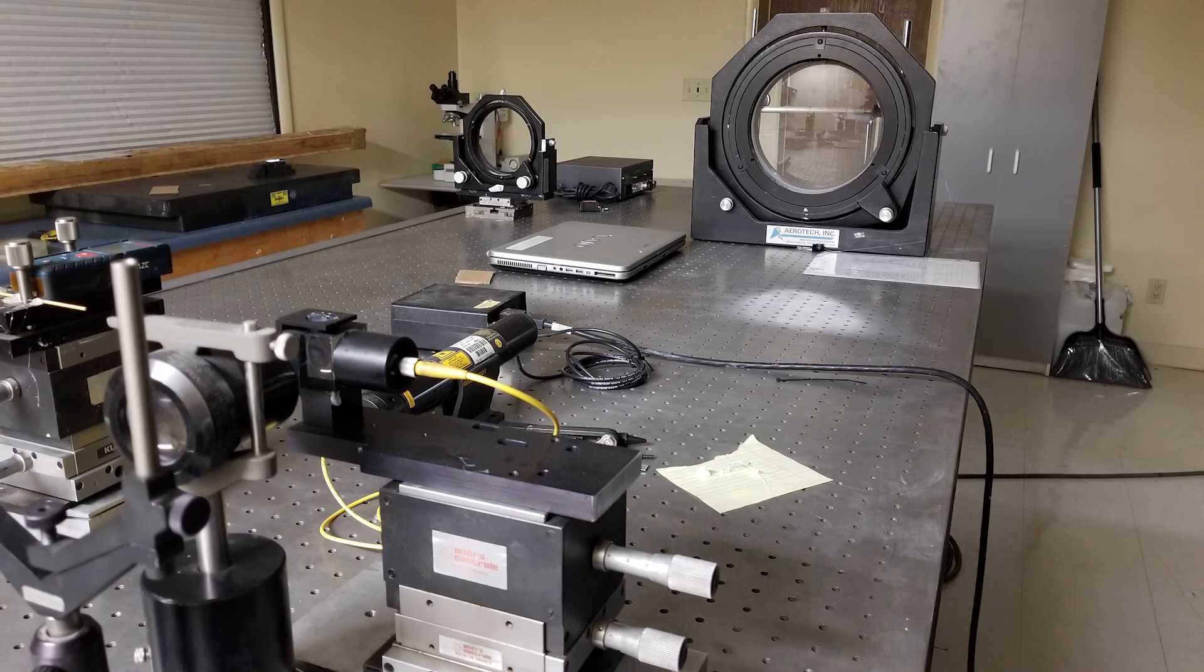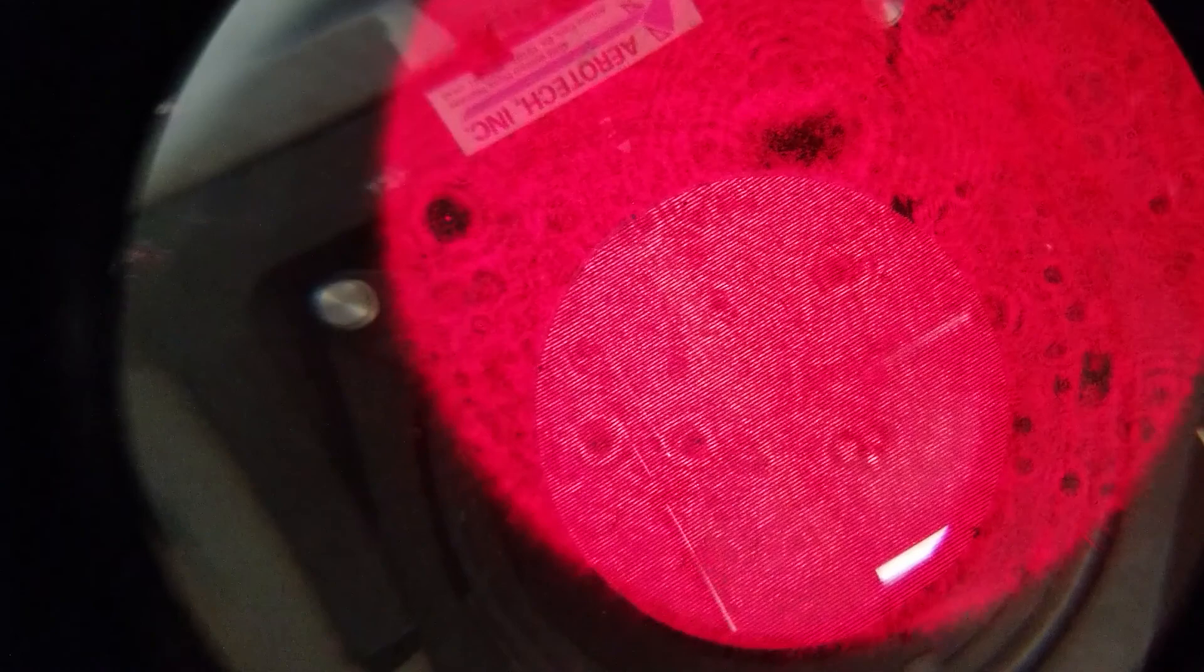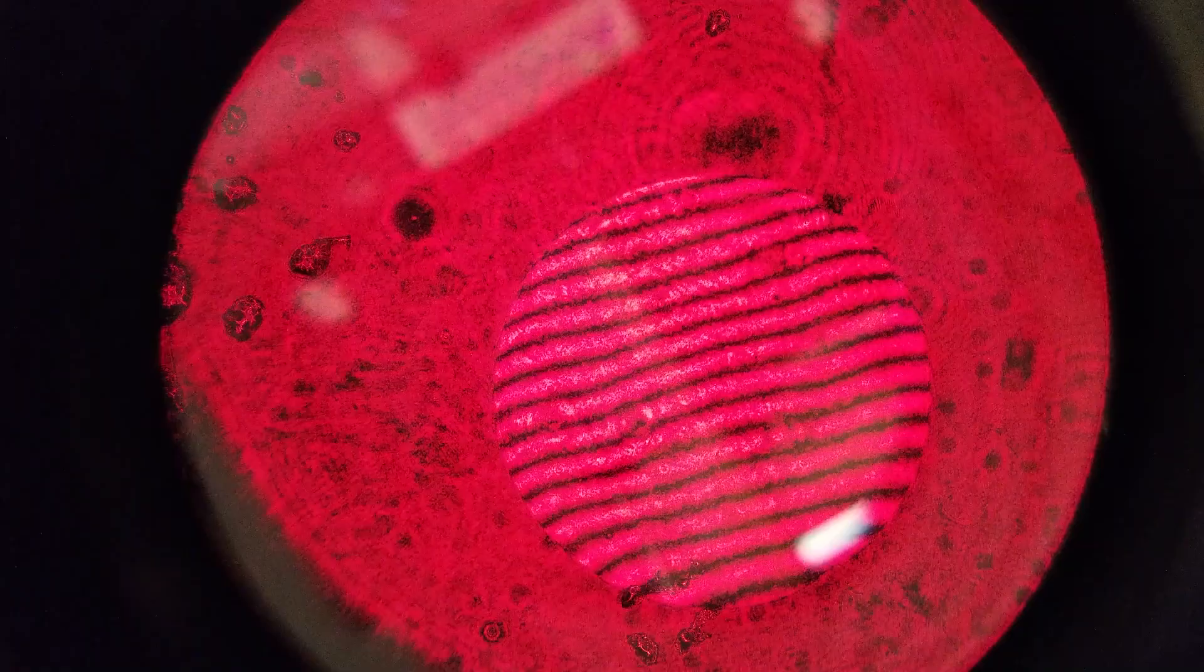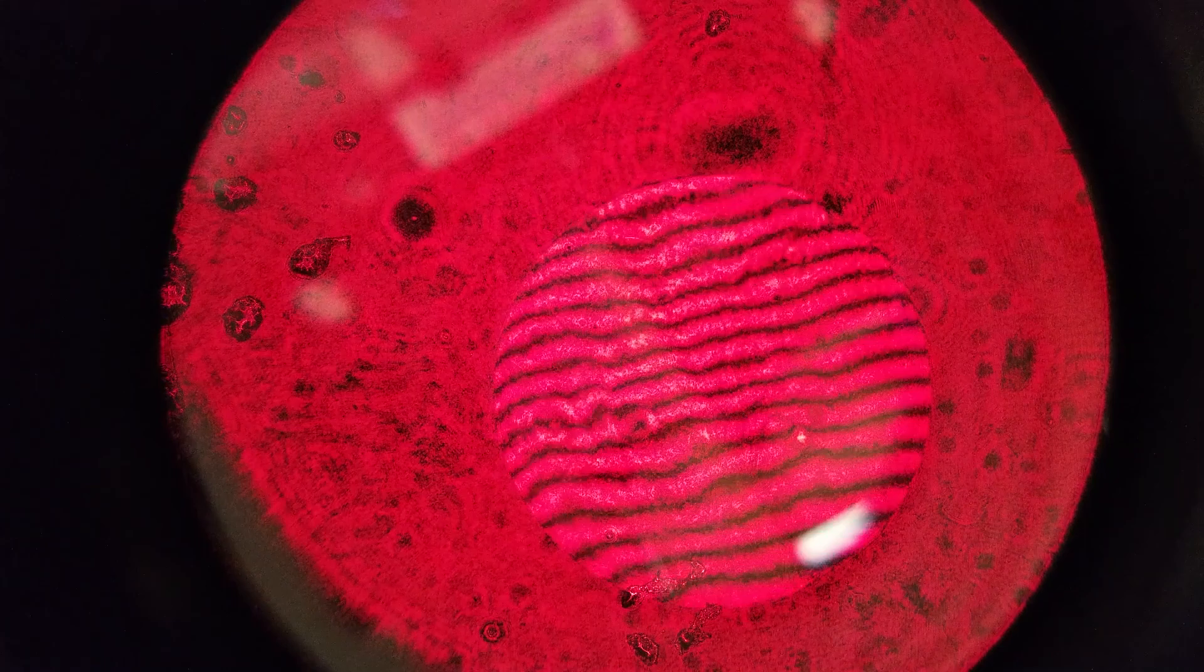The lens tested is set up some distance away from the interferometer, so the light from the laser leaves and diverges from the beam splitter and then reflects and converges back, giving interference fringes. This requires little alignment. We saw a lens aligned and the fringes viewable in only one or two minutes. The fringes can be disturbed by air movement, however.